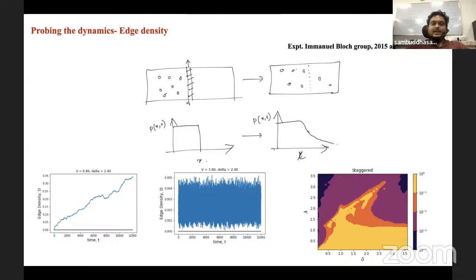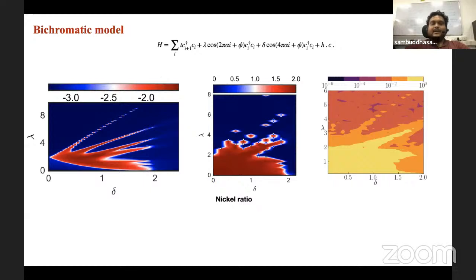So if we do this and we plot this spread in the right half against time, after a long time, and you map it on a color code, you will find the sign of this transition in mobility edge and re-entry behavior, the signature of this in a very much experimentally measurable setup. And we particularly point out that this bichromatic model has already been realized in experiment, and this particular measurement has already been done. If you do this you will clearly see the signature of this transition, and even if you tune the optical lattice frequency, you can clearly see this emergent scale phenomenon.